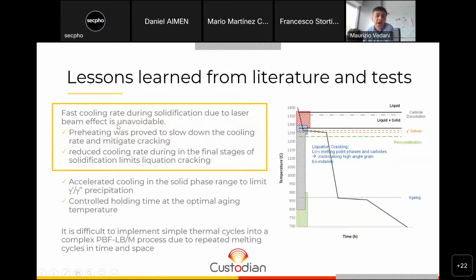We cannot avoid that, but we can use some preheating to slow down the cooling rate a little bit and mitigate the hot cracking. And also, if we concentrate this preheating, or if we can reduce the cooling rate, especially during the very last stage of solidification, then we can also limit and mitigate the liquation cracking. This is the most important strategy for the rest of the project. And again, an ideal thermal cycle could be given by this black line, where we added the time axis on the previous diagram.